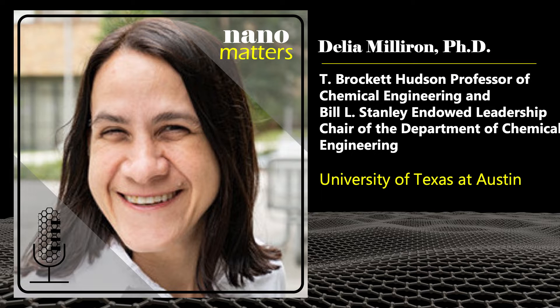Does the switching between modes involve a physical reorientation of the crystals? No, actually the crystals are stationary and they don't really change their shape or size in any particular way. What happens is we add and remove electronic charge through an electrochemical means, which means electrons are moving in and out of the material, and at the same time ions are moving in and out of the material from an electrolyte or salt solution that they're in contact with.